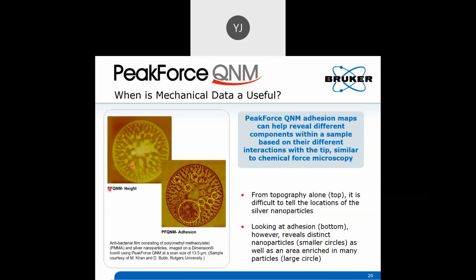Okay, so then you can look at different materials. So here is one of this kind of like a packaging material with silver nanoparticle, which is antimicrobial. And you can see in this height channel, you have no idea where these silver nanoparticles are. But if you do the adhesion mapping, you can very clearly see where the silver nanoparticles are. Even if you do the mechanical one, you can clearly see that.